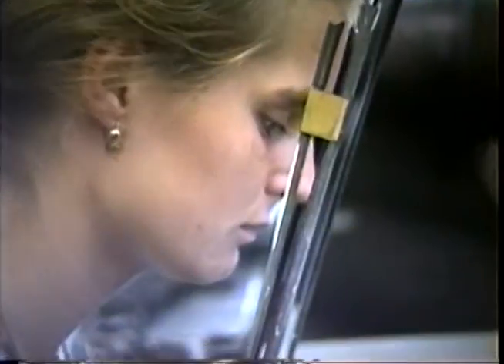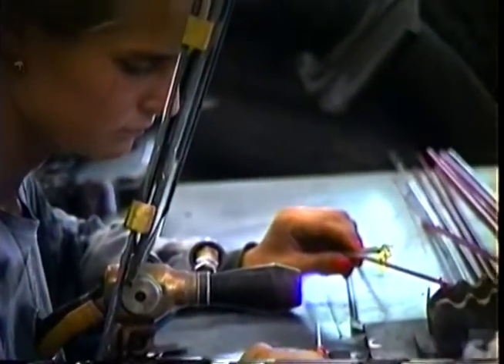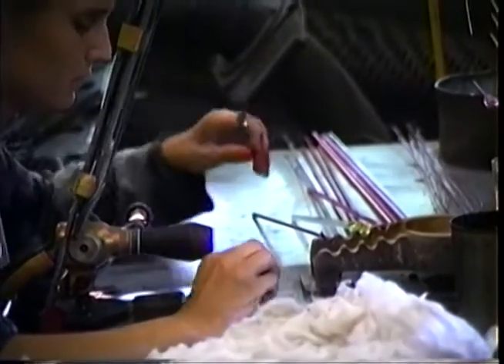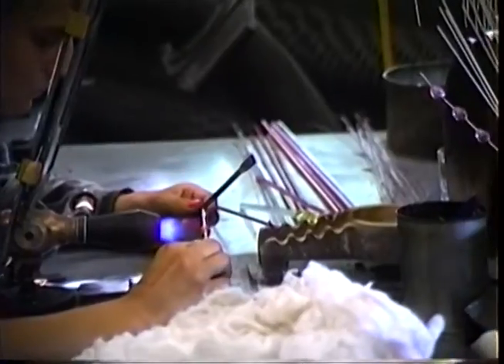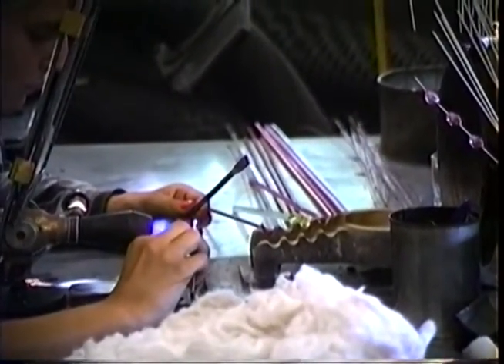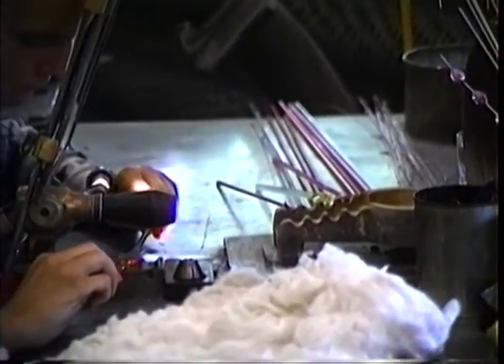Each worker has a double glass shield with an airspace between to protect them. No eye protection is worn. Notice the large nozzle on this torch and how low it is and parallel to the table surface. You can see the cast iron form with the notches for the rods to rest. The flame shoots directly at the rods, warming them.